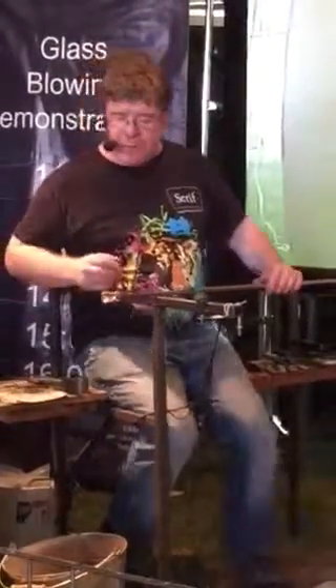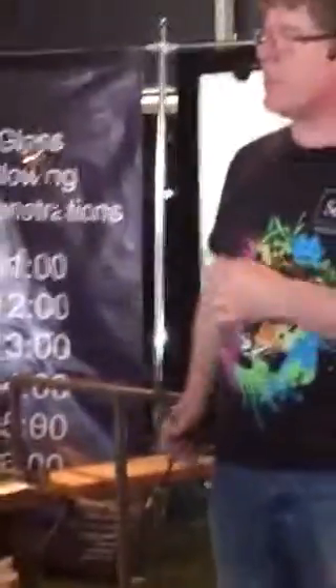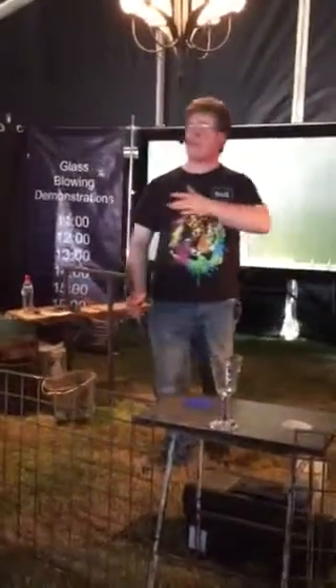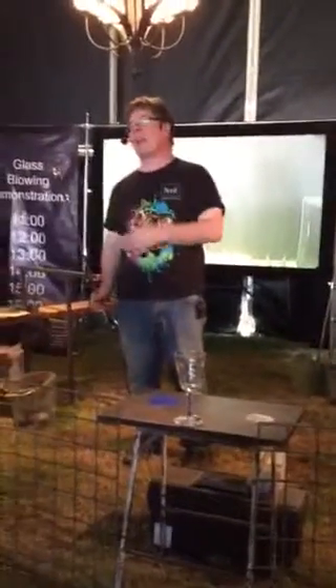Just to give you an idea what sort of temperature we're talking about. It's still around about 700 degrees, it's a big temperature. But to a glass maker it's cold because it's lost its movement, so you can't do very much with it. So what I'm going to do is just hang on to it for a few seconds longer. Let it cool down to 600 degrees, something like that. The reason I want to do that is because I want to go back into the furnace and get some more molten glass on top.